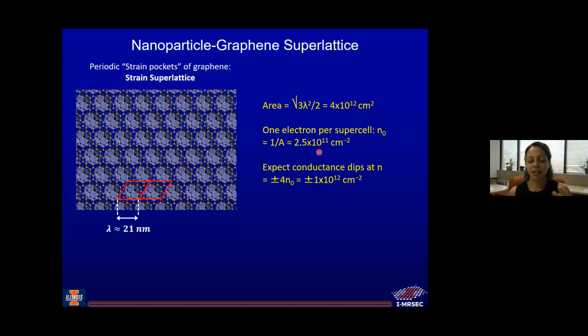Okay, but now we say, well, I know for graphene that we have some electronic degeneracy. It actually has an up and a down spin, right? That can go into the same area. And also it has what we call valley degeneracy due to these multiple Dirac points that you see. Okay, so for every band in graphene, you expect to have 4 electrons. So now we say, okay, let's assume we have 4 electrons for every one of these 20 nanometer areas. That gives us an expected conductance change at a filling of 1 times 10 to the 12 per centimeter squared.